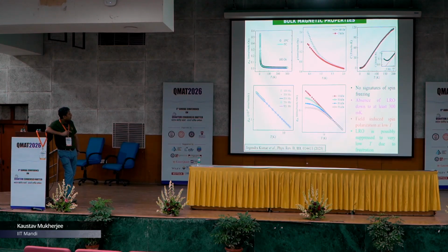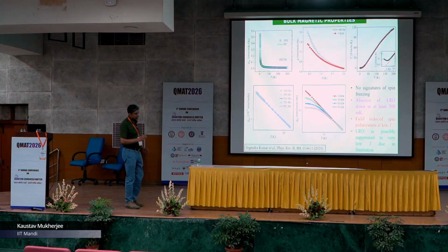We further did a few chi-T and M-H measurements at ultra low temperature. So here we see that up to 300 millikelvin there is absolutely no anomaly. It's a smooth curve which is rising. So from these three graphs, it can be said that in this compound there is no signature of spin freezing. Also, there is an absence of long range ordering down to at least 300 millikelvin. And at higher field we got some field induced polarization effect. But the main thing is that in this YbNbO4 long range ordering is possibly suppressed to a very low temperature due to this frustration effect.